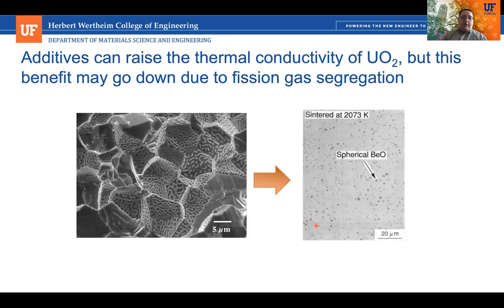However, we're going to get fission products forming, and some of those fission products are fission gas. And we know that fission gas tends to segregate to grain boundaries, and we get these interconnected networks of bubbles along grain boundaries, and that's how we get fission gas release. So now if we throw in these particles, we're adding additional interfaces for fission gas to segregate to, and interfaces that are probably going to have more free volume than a grain boundary. So they might be even more preferred segregation sites than the grain boundaries themselves.